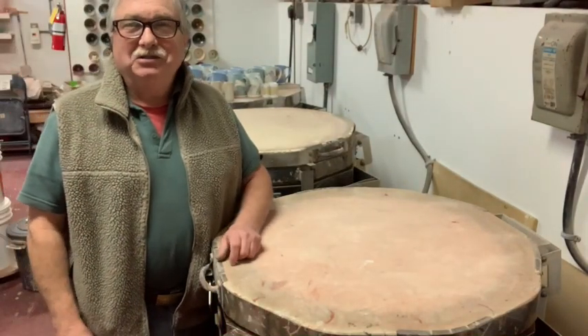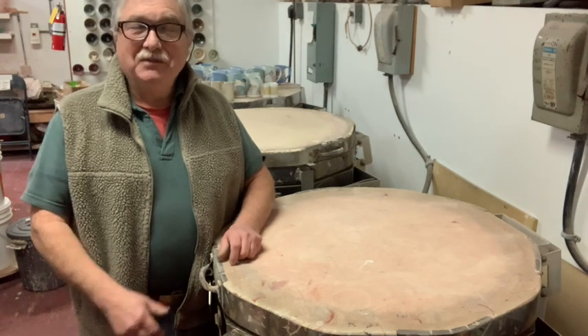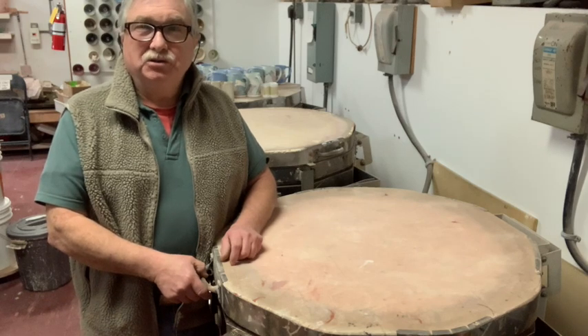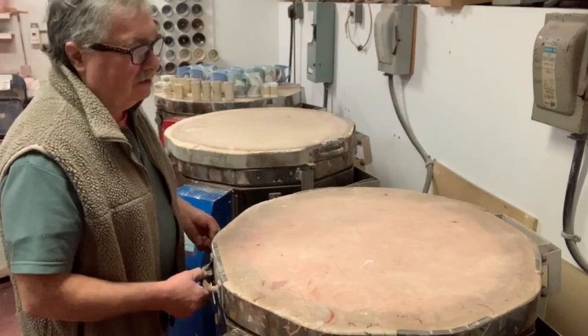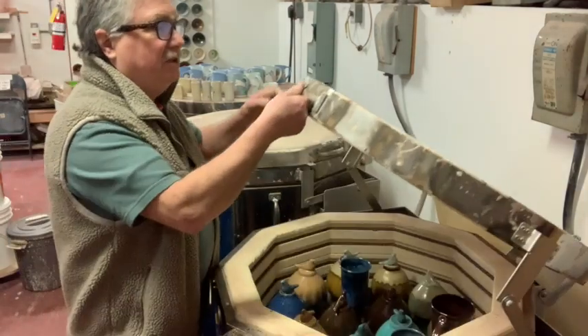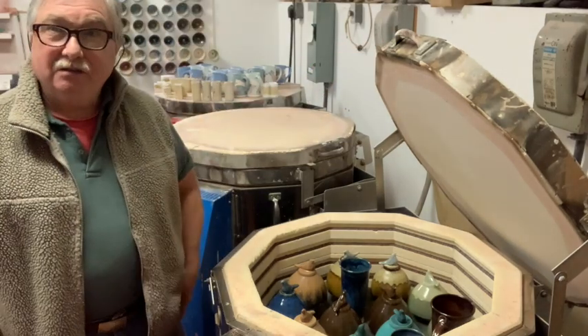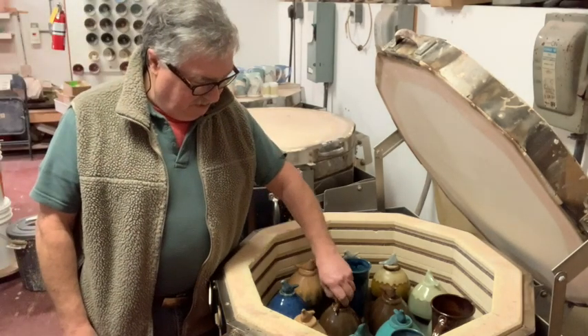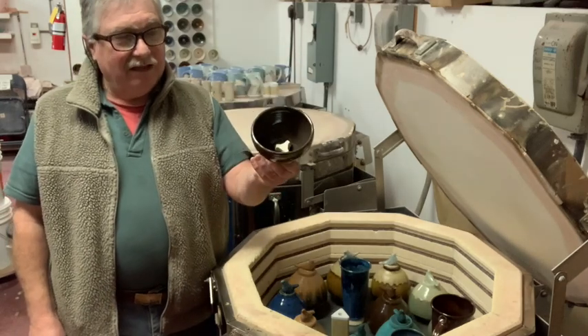Good morning. I just showed you a beautiful video — we have to be in a great mood now, this is just spectacular. But even more so, I did a change in firing here with a shorter soak and a 7-degree lower peak temperature. So let's see what happened. Remember I said that things were running too much down. I'm not expecting much from my Randy's Red because that likes the long soak. So there's my first Randy's Red — goes back to brown. That'll have to be re-fired.